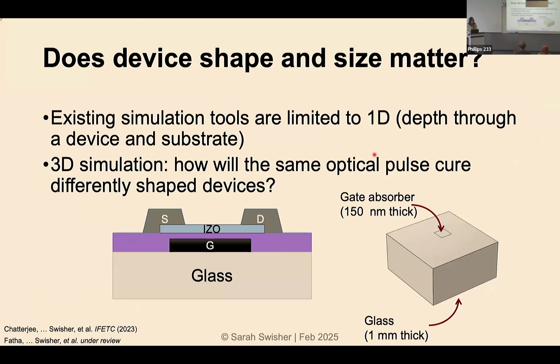And so this is something that we wanted to explore, because the whole benefit of being able to do this large area processing is that you can do lots of devices at once. And if they're going to be processed at different temperatures, that's something you have to design for. The existing simulation tools that we had were just looking at depth, looking at material thickness as a function of depth. So we developed a 3D simulation so that we could determine how that same optical pulse applied over a large area is going to cure devices that may have different geometries.